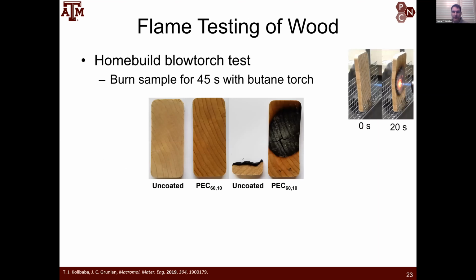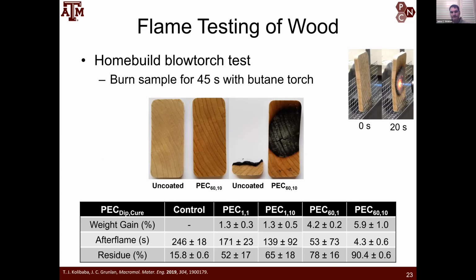And then if we hold a torch for 45 seconds on the wood, you can see that it only forms char, it does not catch fire. But the uncoated wood, of course, burns up completely. So below you can see we are looking at after flame time of the wood and the residue of wood that's left behind. And you can see the best coating that was only adding 6 weight percent to the wood maintained a 90% residue, which means basically the wood didn't burn.